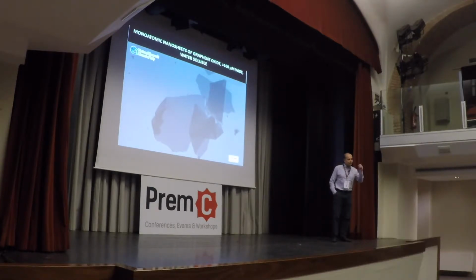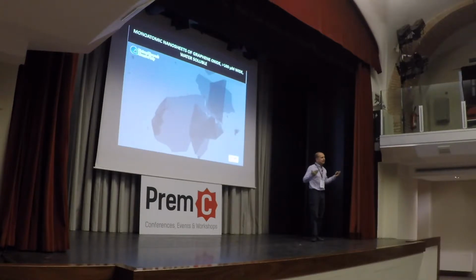Because of its perfection, graphene is a very nice crystal. It does not like to interact with other kinds of objects. So we still have lots of problems of solubility of graphene, of processing it, of producing it. And even now, to produce graphene, you need to put in a lot of energy. Lots of sonication, you need to have high volume solvents or soaps, and you never get these kinds of things.